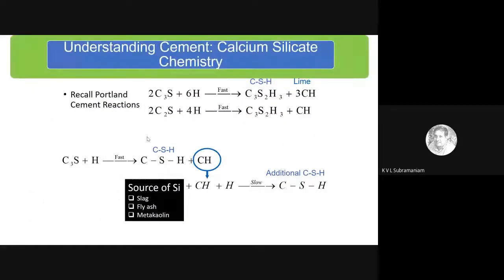And the way we use these supplementary cementitious materials is in a cement system. So I have my cement reaction between the calcium silicates and water, which leaves a lot of lime. So what we do is we look at these supplementary cementitious materials, which are primarily sources of silica. Most of the materials that we have, whether it is slag, fly ash, metakaolin, or silica fume, are rich in silica. So these bring in the S element in the reaction. Because the cement hydration leaves CH, which is calcium hydroxide, if I bring in a source of silica in the form of either fly ash or slag, that would consume this CH and give me additional CSH. And this is what we call our pozzolanic reaction.